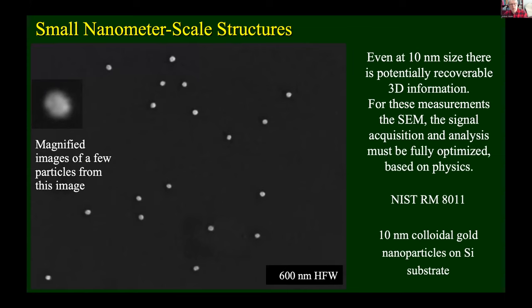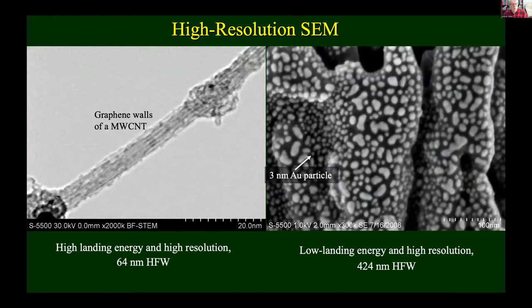Even at 10 nanometer size particles, what you see moving here on the left side is me playing this particle in a digitally magnified form, and you can see there is contrast. There are shape and intensity differences which are tied to the number of atoms. Again, this particle is made of a few hundred atoms. SEMs can resolve carbon nanotubes, multi-wall or single wall, can show very tiny particles, gold nanoparticles in this case, but platinum particles in lithium batteries and other things.